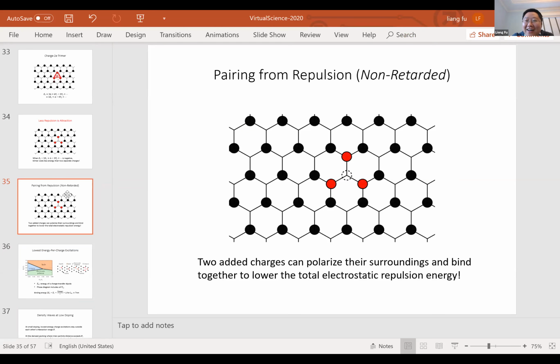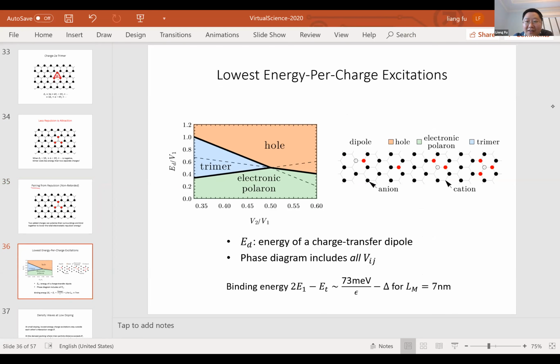So this is the key result. So basically, even in this classical system of charges with repulsive 2-body interactions between any 2 charges, what we see is that we can get pairing directly from the repulsion. And this pairing is non-retarded. We're not using any quantum mechanical effect, right? So with this, then the rest becomes straightforward.